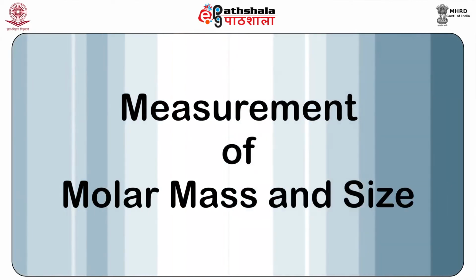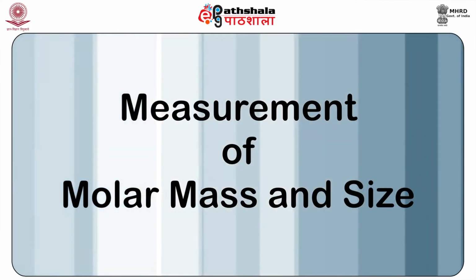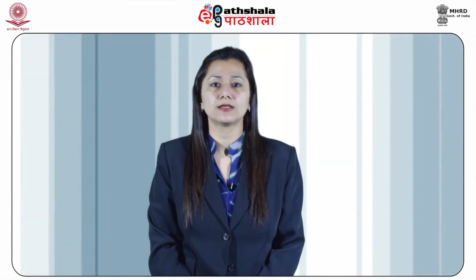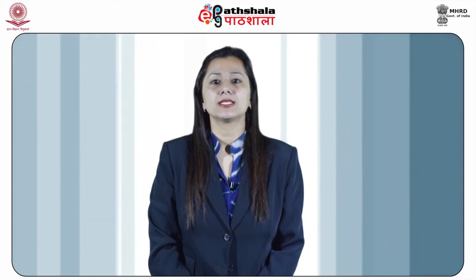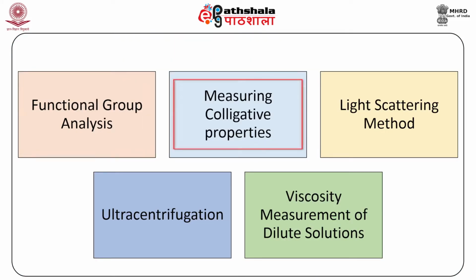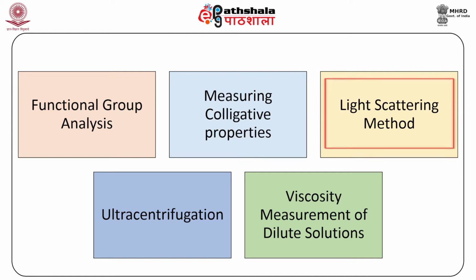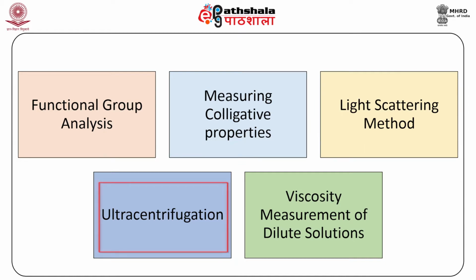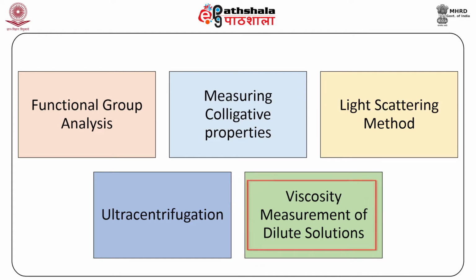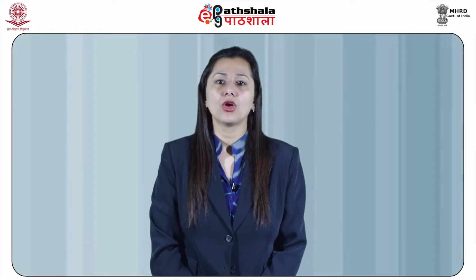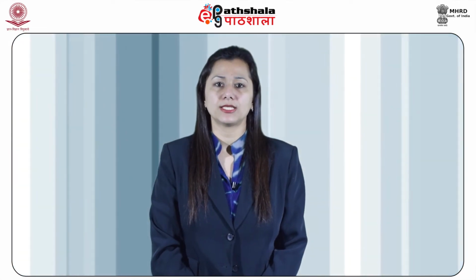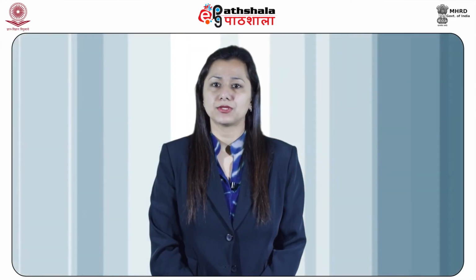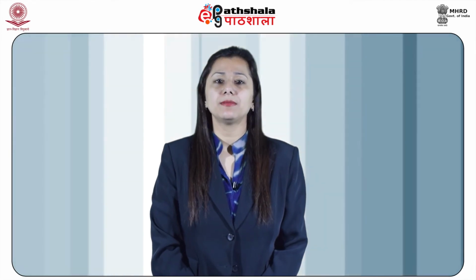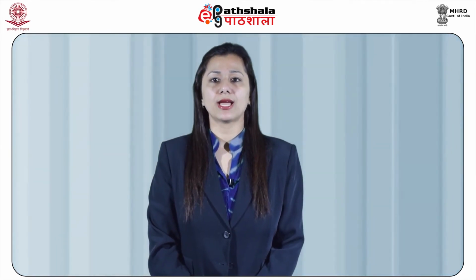Now, we shall see the measurement of molar mass and size. The molar mass of polymers can be determined by a variety of physical and chemical methods such as end group analysis, by measuring the colligative properties, by light scattering method, by ultracentrifugation, or by viscosity measurement of dilute solutions. All these methods except the viscosity method are in principle absolute. That is, molar mass can be calculated without reference to calibration by some other method.